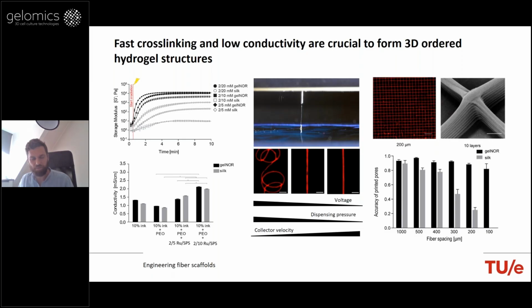We went down to 400 microns with a printing accuracy of around 80%. This printing accuracy means the deviation between what you designed and what you printed. And below 400 microns, there was a significant decrease of printing accuracy. So we started to lose the ability to lay down patterns, or to lay down fibers, in a controlled way. And this was more evident for the silk material.